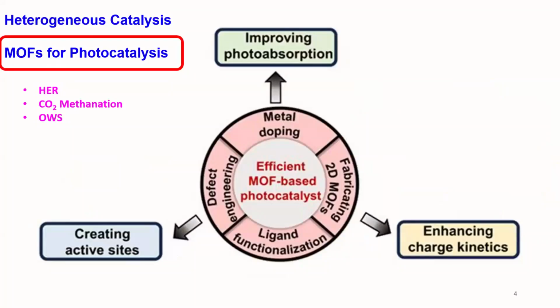So far we have been working on heterogeneous catalysts, but recently we moved our interest to photocatalysts. As I mentioned, we wanted to use MOFs as photocatalysts for 3 reactions: the hydrogen evolution reaction, CO2 photomethanation, and overall water splitting. For any catalyst to be a highly efficient photocatalyst, it has to improve the photoabsorption through metal doping, and the MOFs can also be fabricated for enhancing charge kinetics, especially to separate the holes and electrons, and to create more active sites. So one has to create defective sites and also functionalize the ligand, because it has to absorb visible light and it has to create more active sites. These are some of the basic requirements in a MOF catalyst.